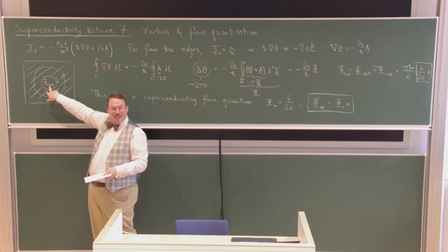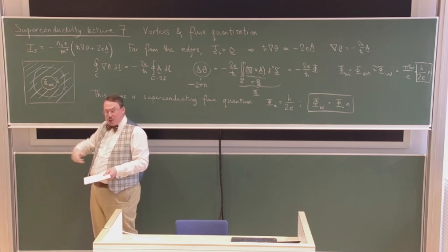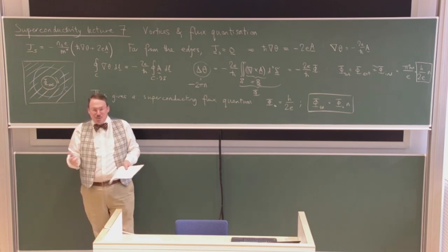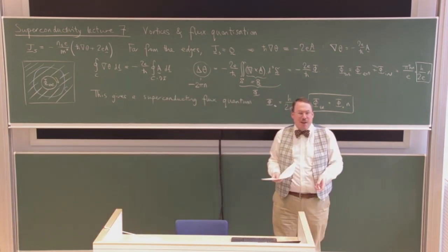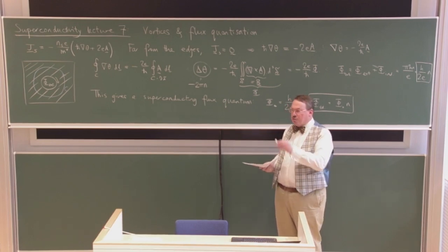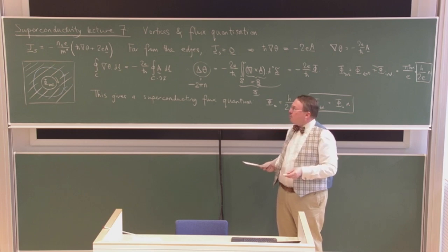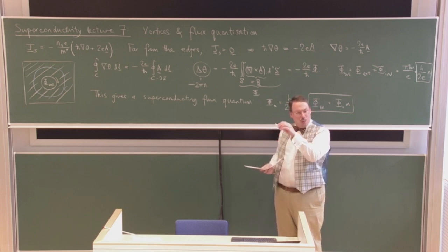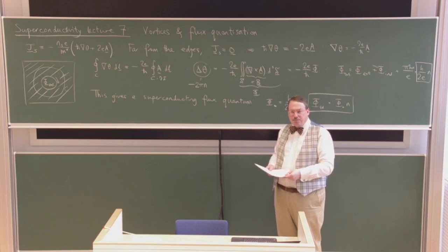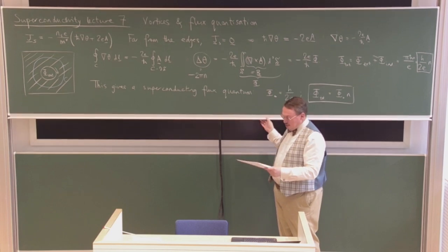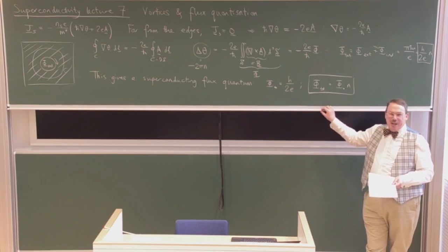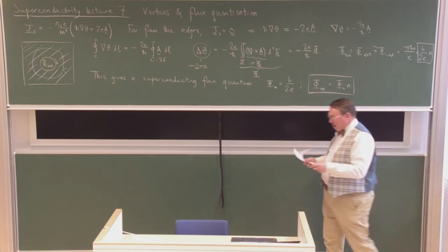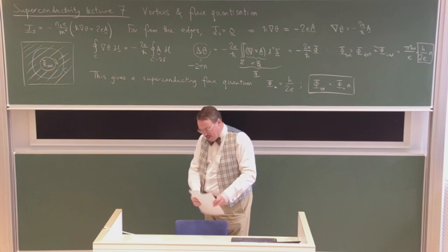And those are genuinely degenerate states, and if the superconductor is small enough, you can kick it between those two states, and there are qubit designs that are basically based on that fact. So you can use those two circulating states of the supercurrent, one anti-clockwise and one clockwise, as states of a qubit. Good. So that's actually quite a simple observation, but it has weird consequences. So I thought we'd start there, and then think about how these cavities might come about.